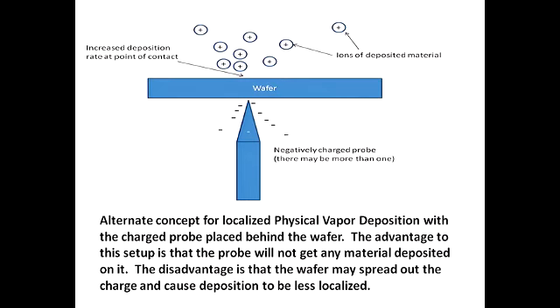Another way to do this method is using the probe on the opposite side of the wafer. We want to have deposition in this area, but our probe is behind the wafer. By changing the location of this probe and also changing the amount of charge on that, we could control the deposition rate and also the position of the deposition. This method is better than the previous one because we are not worried about the deposition of metal on our probe, and the disadvantage of this is that maybe the wafer spreads out the charge and causes deposition to be less localized.